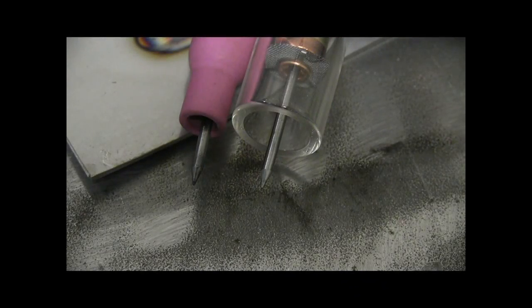So you can easily see how the tungsten on the right versus the tungsten on the left is much cleaner, maintained its shape very well, maintained its color very well, and so it's going to produce a higher quality weld and a more stable arc for a longer period of time. And so when you get in a situation where you need to stick the tungsten out of the cup to get access, it's always better to use a gas lens.